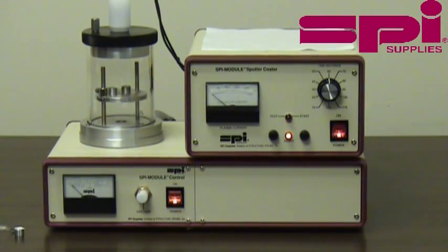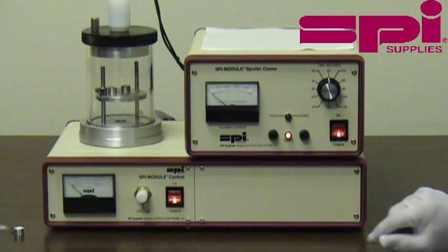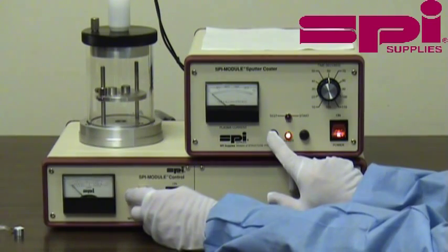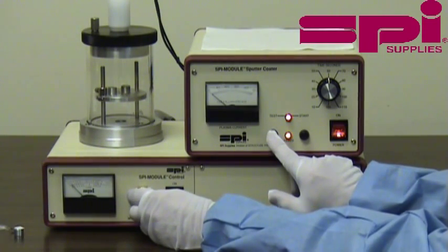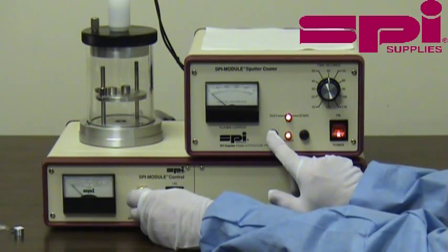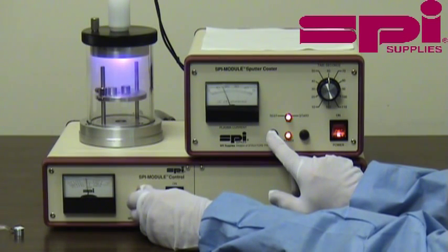Prior to coating, make sure to set the desired coating time using the selector knob. It is also recommended to use the test button to set the desired discharge current. This is accomplished by pressing the test button and adjusting the needle valve on the vacuum control base to achieve the desired discharge current. Typical operating conditions are around 18 milliamps.